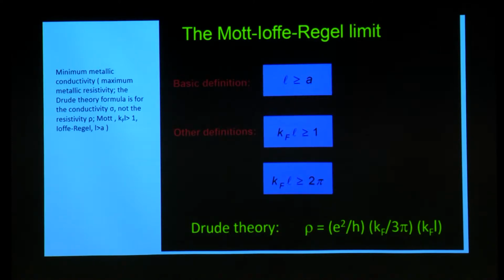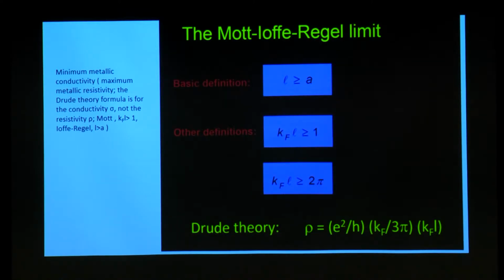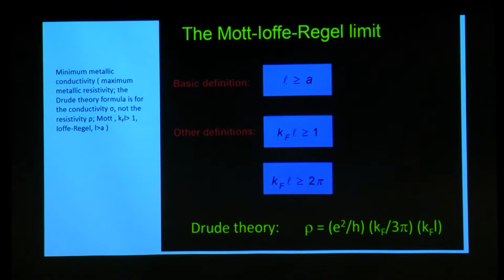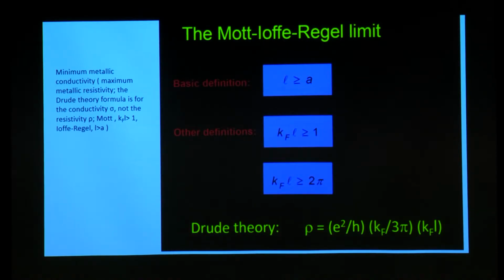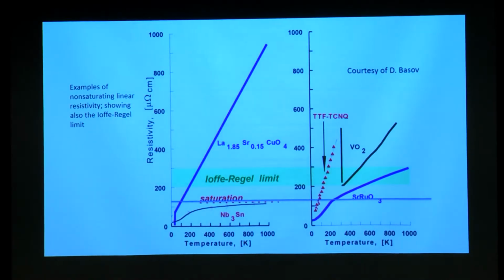Many metals actually respect it, and it's an old observation that many disordered thin films have a resistivity either less than 30,000 ohms or several megohms. The resistivity has to be either less than 30,000 ohms or it's an insulator. Okay, but fine, let us see what actually happens. Then I'll go to the more primitive approach.